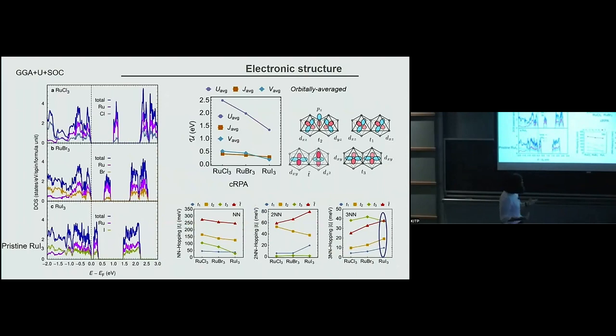And what I have to say is that in this calculation, you really need to include the iodine. You cannot just make an effective ruthenium model, you have to include all the processes through iodine. Otherwise, you don't get that. But this is the key point. If we don't get that, then we're done. There is no localized model.